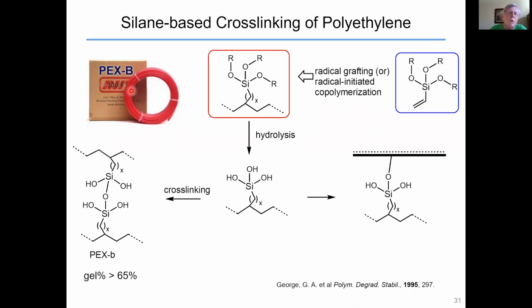If you look at your hot water pipes, if it's plastic, it's probably PEX, so-called PEX B. If you take this polymer and expose it to steam, you clip off the ether groups to generate these silanols, and then these cross-link to make siloxane linkages. This material then is cross-linked polyethylene, quite impervious to further hydrolysis by water. This has also been used to bind these polymers to surfaces.